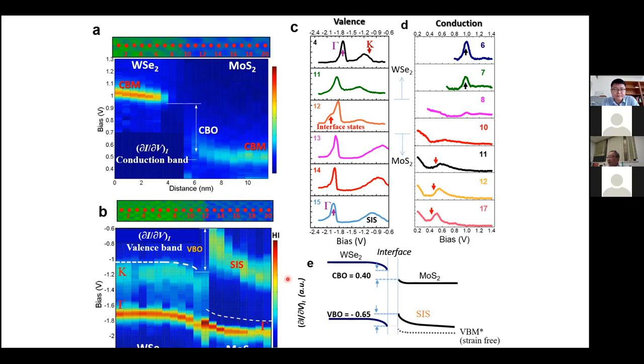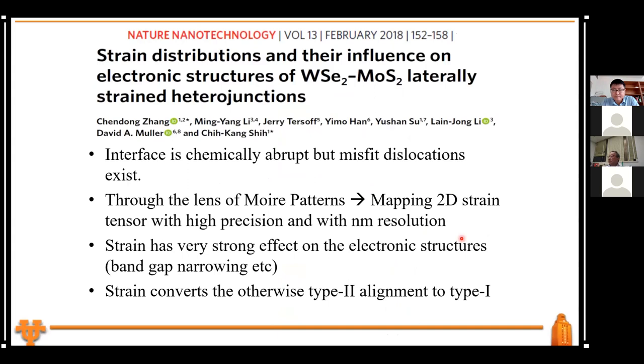But it turns out you have this strain-induced interface state, and that pulled this up and changed what used to be a type 2 interface. In this case, it becomes a type 1 interface. Okay, type 1 band offset. So that's kind of interesting.